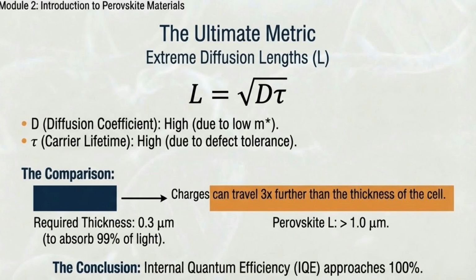First, as we just learned, their incredibly low effective mass gives them a massive diffusion coefficient. They move fast. Second, perovskites possess a unique property called defect tolerance. When defects do form in the lattice, they tend to form shallow energy traps rather than deep ones. This means charges rarely get permanently stuck, leading to incredibly long carrier lifetimes. When you multiply a high velocity by a long lifetime, you get an extreme diffusion length. In high-quality perovskites, diffusion lengths easily exceed 1 full micrometer.